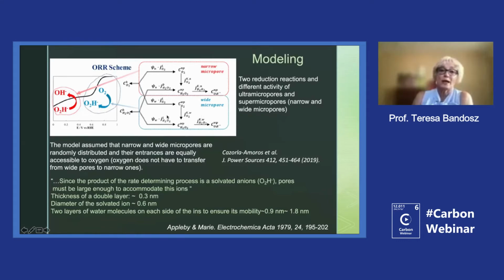So in wide micropores, we have the oxygen reduction to the peroxide, and then in narrow micropores, we have the reduction of the peroxide to OH minus. It is quite interesting because it might explain the shape. I may go to the shape later, but if we look at the calculation by Appleby and Marie, so those narrow micropores, the question is what could be their size?